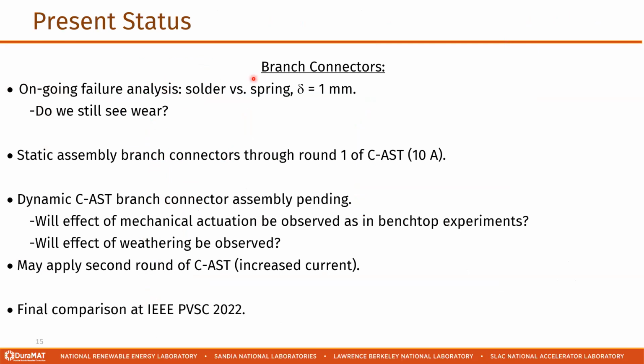So presently, we're looking through the branch connectors, looking at the failure analysis of the latter experiments where we're using a 1 millimeter deflection. Will we see evidence of wear in these samples if we've turned down the actuation? We've run a set of the static assembled branch connectors through a round of CAST. We ran that through at 10 amps. And then we're presently working to complete the texture for the dynamic CAST test.